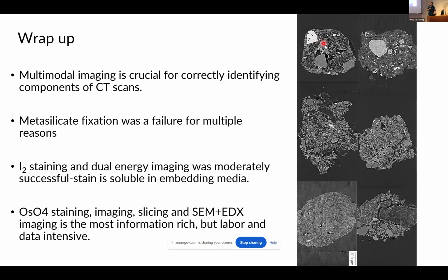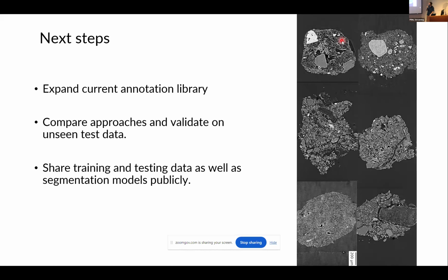There are a lot of soil aggregates out there that are pretty different looking. This is from an andisol. This is from a histosol. I don't know if we'll ever be able to segment odd soils really well. You can see, so this might look organic, but it is 100% volcanic. And so that's just a silicate up there. I don't know if we'll ever be able to segment those extreme examples, but I think that we're getting to a point where we will be able to segment visible organic matter from almost any CT scan, and then potentially segment other chemistries.